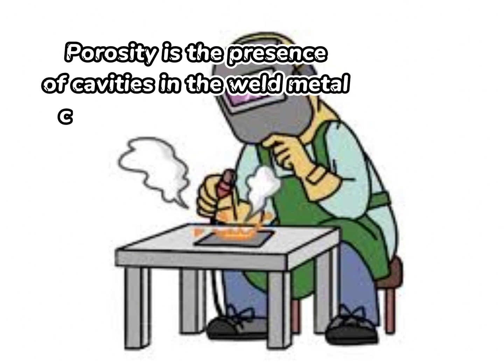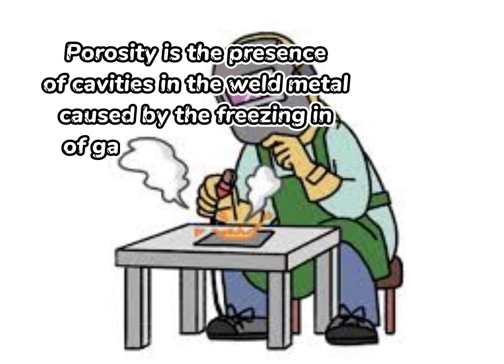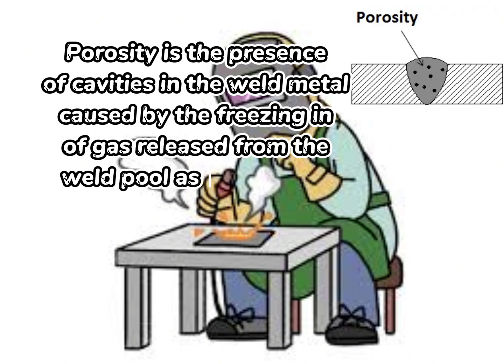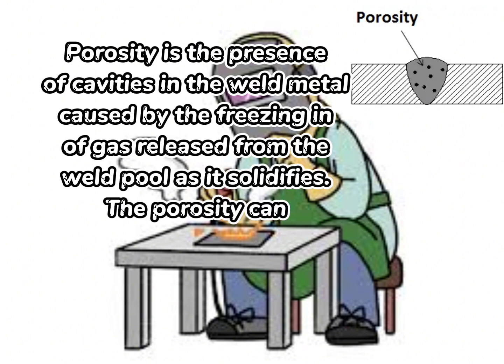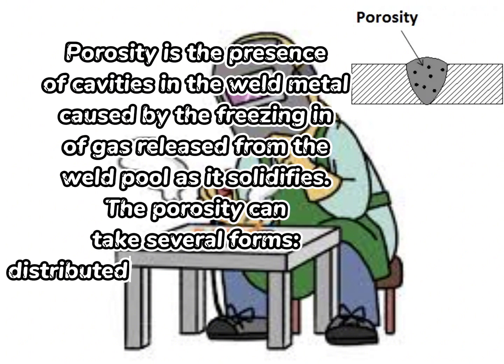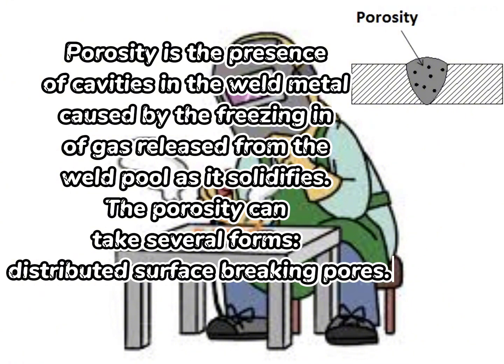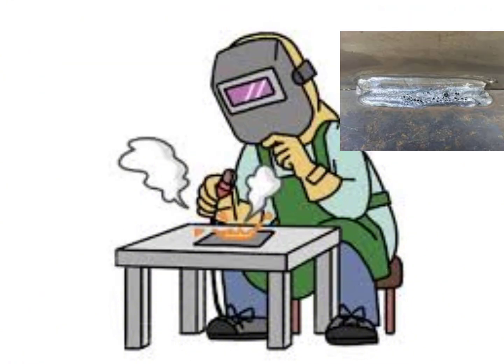Porosity is the presence of cavities in the weld metal caused by the freezing in of gas released from the weld pool as it solidifies. The porosity can take several forms: distributed, surface breaking pores.